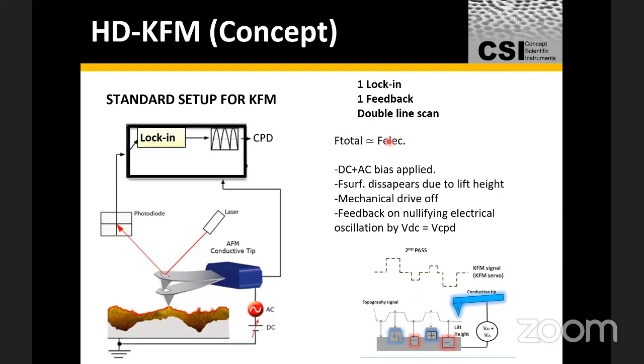But obviously, to be able to get measurements on a surface with a cantilever, you want your cantilever to hover as close to the interaction area as possible. To be able to do that, in the last 10 years, the concept of using multiple frequencies to make simultaneous multiple measurements was introduced. What we do now is we don't lift the cantilever anymore, but we simultaneously measure the topography of the surface and its work function or electrical properties by oscillating the cantilever at a different eigenmode, a higher harmonic, and using two lock-in amplifiers at the same time. One locks into the topography signal, and the other locks into the functional signal, that is the electronic measurement.